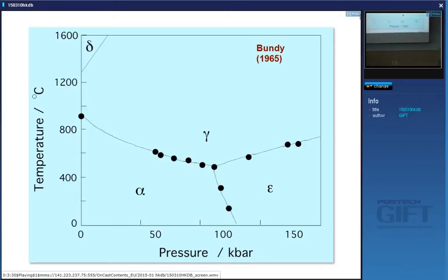But alpha iron, which is ferromagnetic, will have the magnetic spins aligned, right, along one set of axes. So that's no longer cubic. Cubic means you have cubic symmetry, and the spins would be pointing in all directions. But if it's ferromagnetic, then the spins are all aligned. So it's no longer cubic. So the old idea of beta iron was correct in one sense, that as soon as you go below the Curie temperature, the lattice is no longer cubic.